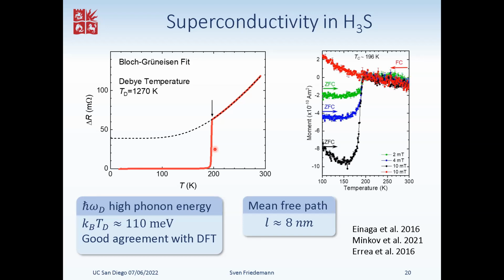Evgeny Talantsev has done this in quite some detail. Essentially, he's cooked up a global fit function which includes the step at Tc and hence extracts Tc and takes the electron-phonon coupling, and he comes up with a variation of Coulomb parameters, but typically of the order of 0.15, 0.13. So it is similar. It's smallish, yes. Small.